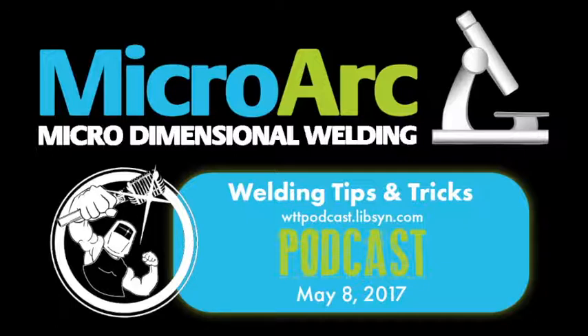Cracking is the biggest thing when welding high alloy tool steels. The block can be sitting on the bench, and all of a sudden you hear this ding. It's like, oh, what the hell was that? Never want to hear that. Oh, that is the worst thing. There are so many challenges. I've welded jobs where it was A2, and usually it's not a good welding material. Sometimes it'll weld okay, and the next job you just touch it and it'll crack. It depends on how it was tempered after it was heat treated, and you don't know that. There are so many unknowns when you grab a block like that.